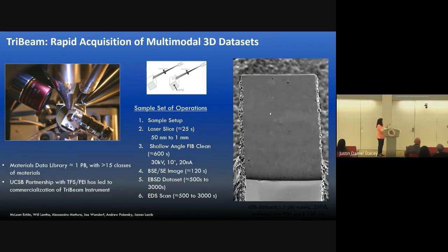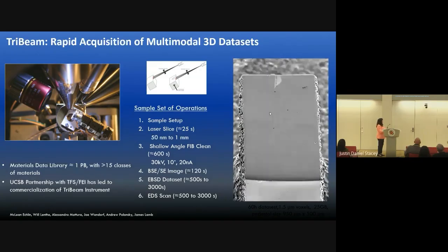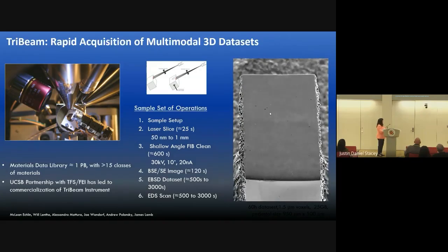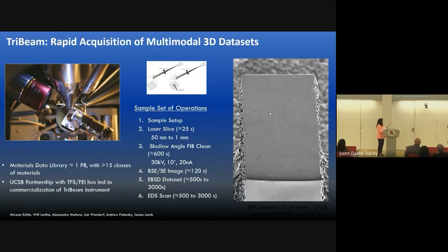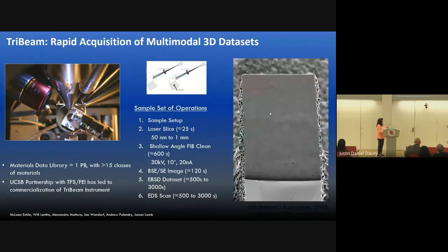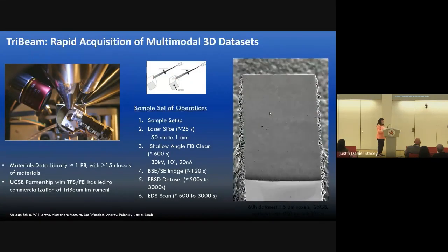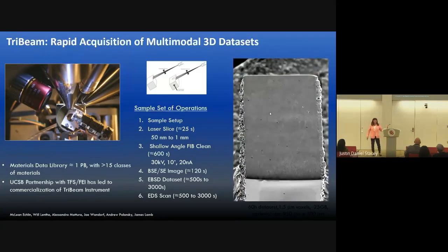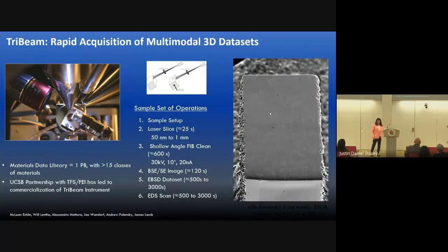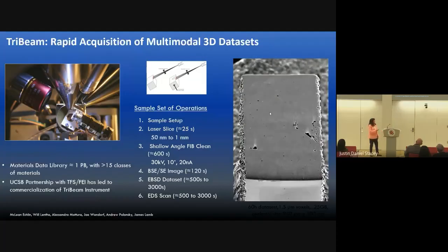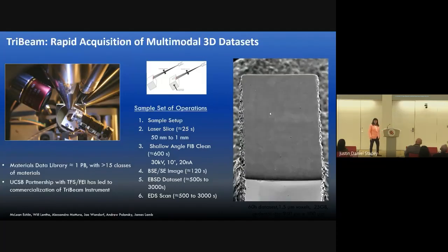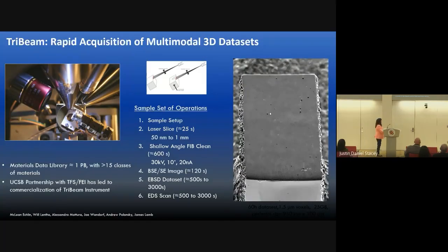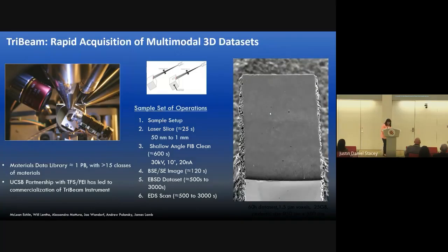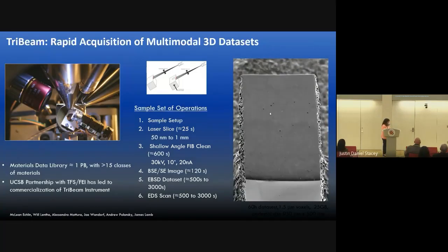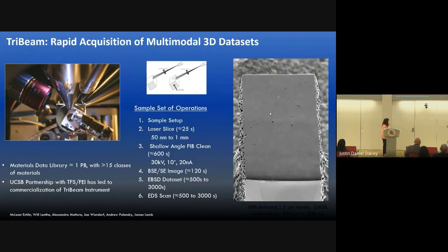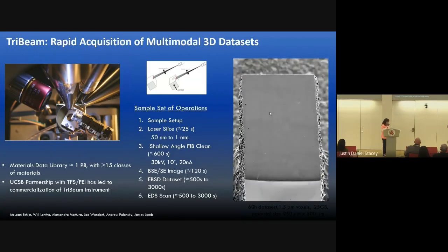So this is sort of a typical workflow, and the real benefit of the femtosecond laser, beyond not doing any collateral damage, is that it's really fast. If anyone's ever tried to make a FIB data set, with this you're able to make a slice in 25 seconds. And then the slow steps are some of the analysis that comes with it. So we are working on making these things faster. This part is now very fast.